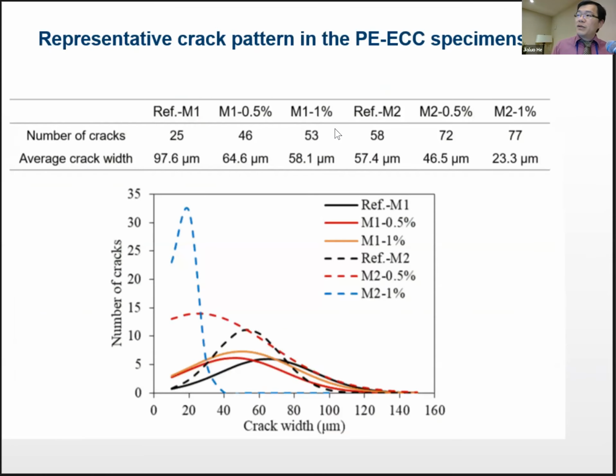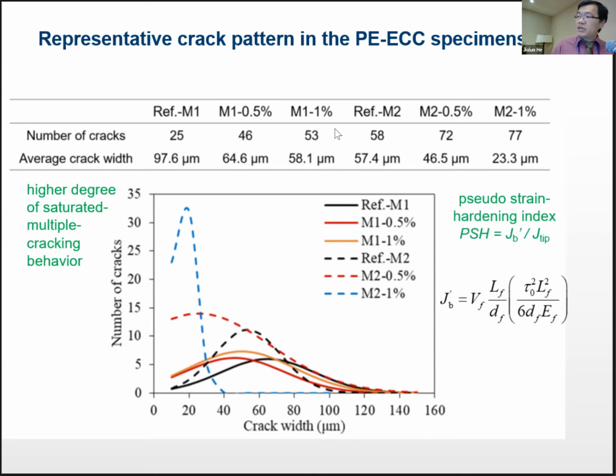And when we quantify it, what's interesting is you're seeing, like I said, M2 series 1%, the micro cracks average only 23 microns. So you see that blue dotted distribution, the Gaussian distribution, it's shifted way to a narrower range. That helps the self-healing. So we're seeing this kind of better behavior as ECC.